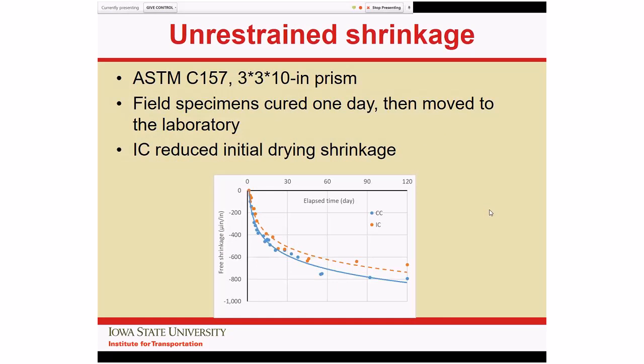All right, we also measured shrinkage. Samples were taken using the prism test, run back to Iowa State University's lab. And again, what we're seeing pretty clearly, the internal curing had a slightly lower free shrinkage, and that's altogether a good thing because shrinkage is related to cracking.